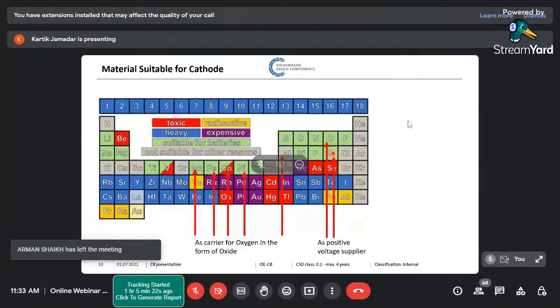Another research direction that is going on is to use sulfur as a cathode material. Sulfur gives you low voltage but a very high capacity. It's a very interesting material. But most of the research and most of the present technology is focused on three things: nickel, cobalt, and manganese. These are the metal oxides which are going to be used in the future, and this is giving us more or less, I would say, 300 watt hour per kilogram.